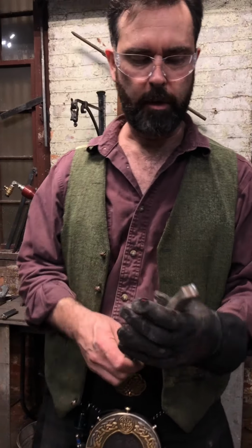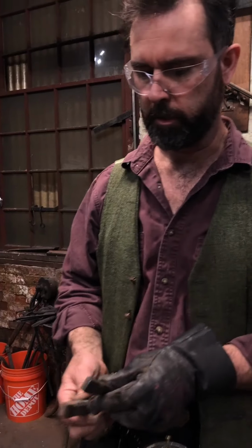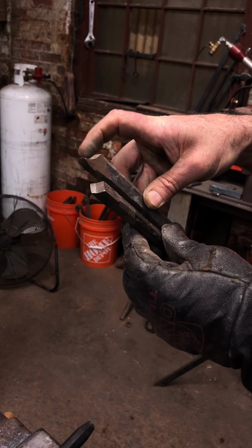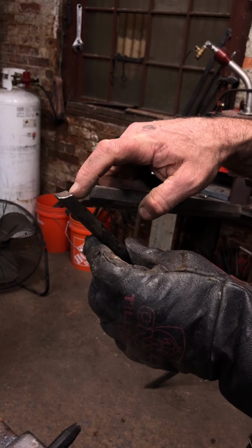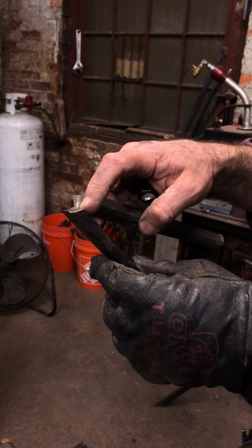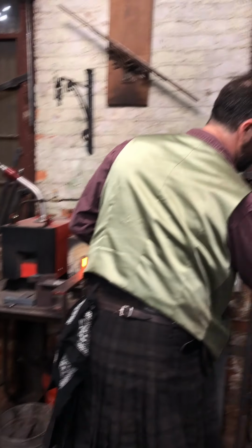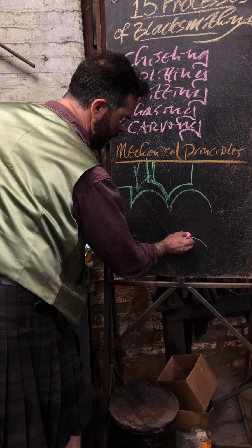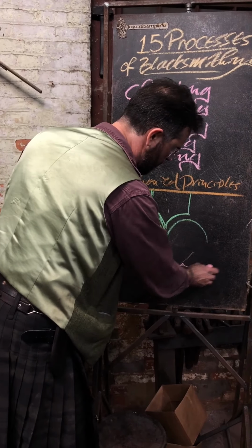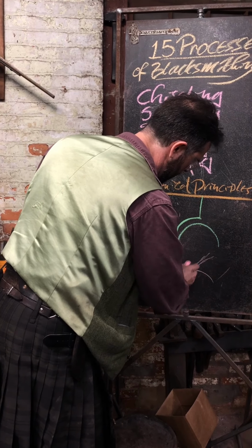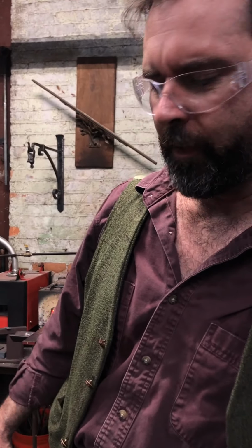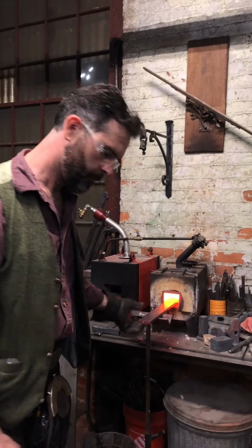Maybe. But yeah, it's just about creating profiles and making the material do what you need it to do. But you see that the radius on those are essentially the same. I put more shoulder in here for blend out, because this can sometimes leave with a slight center, what would you call it? Like a little center peak. So it comes up like this, and at the top you get this kind of like little nipple ridge that runs all the way down it. So that would then run down the center of your crest, running like that. So, you know, you do things enough, you figure that there's problems with it, so you make modifications.